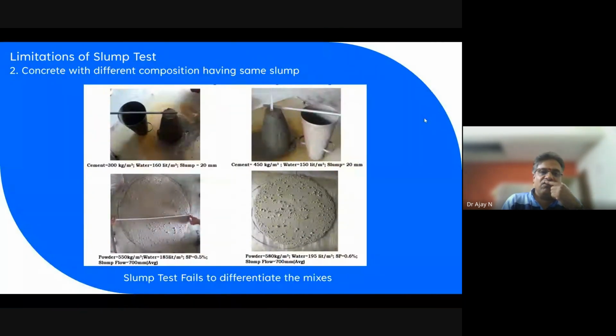Again, another experiment we have done with different mixes. These are all experiments we conducted in 2018. Here we choose 300 kg cement, 160 liters of water, without any admixtures. I am getting 20 mm slump. Again, I am using 450, the maximum cement content, while 300 is the minimum cement content as per the code provisions. Here also I am getting 20 mm slump. So here also I cannot differentiate the mixes.